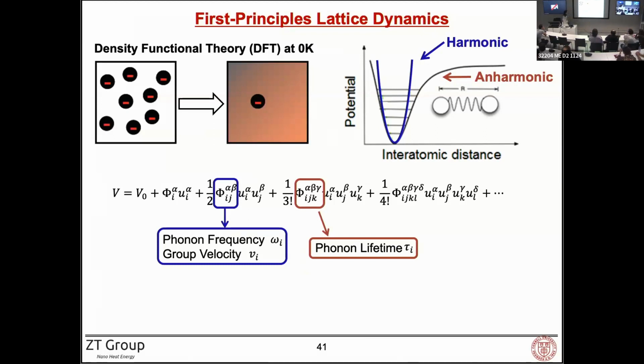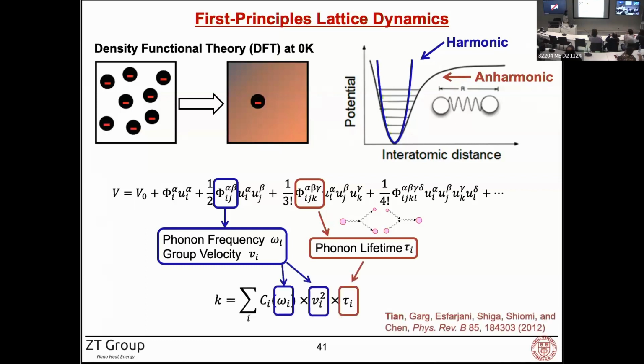Now, because the lifetime is the most difficult quantity to obtain, let me elaborate a little bit here. In a 3 phonon scattering process, 1 phonon can split into 2 or 2 can combine into 1. Now, by choosing just 1 phonon mode, we can screen all the other modes which satisfy the scattering conditions by looking into the energy and momentum conservation rules. And then we use Fermi's golden rule to evaluate how often those scatterings happen to calculate the scattering rate, and then we can obtain the lifetime. And then we can combine this into the thermal conductivity, and that is what we started doing a decade ago. And it showed great success in capturing the thermal conductivity behavior of a lot of inorganic crystals.